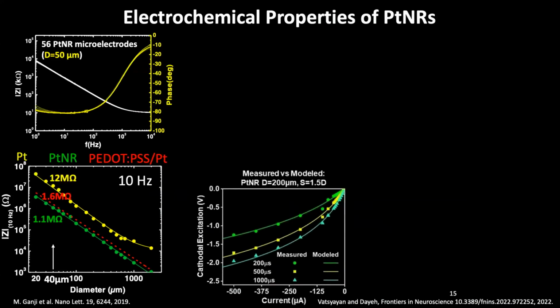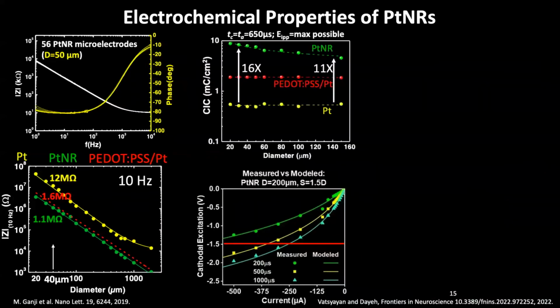And we do parametric studies for different pulse widths, different currents. And we want to make sure that the voltage that's being dropped is below the voltage that we estimated from the cyclic voltammetry. And that will be our current limits, or define what's called charge injection capacity, the total amount of charge that's normalized to the area.